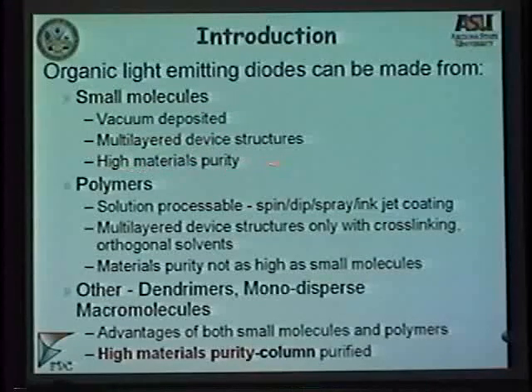They become very expensive, but also you need to deposit them in vacuum. You cannot deposit small molecules directly from liquid processing. Polymers, on the other hand, you can inkjet print them, you can spin coat them, so that is good, but purifying them is extremely difficult. It's impossible, actually. And that's why polymers, this is one of their weak attributes at the moment, is the purity doesn't match this molecular purity, and therefore the device performance isn't as strong, as long-lasting as the small molecules.